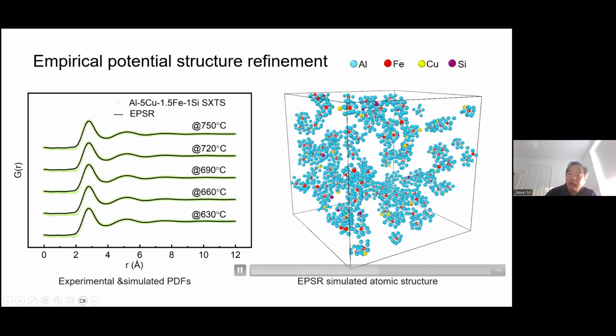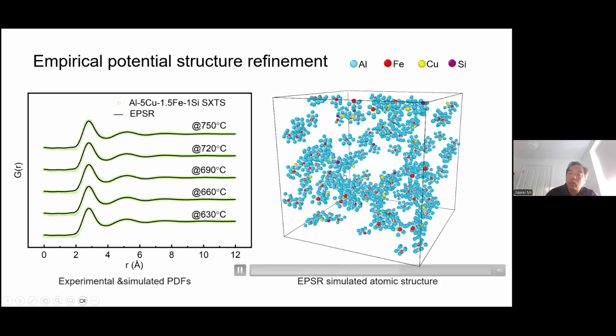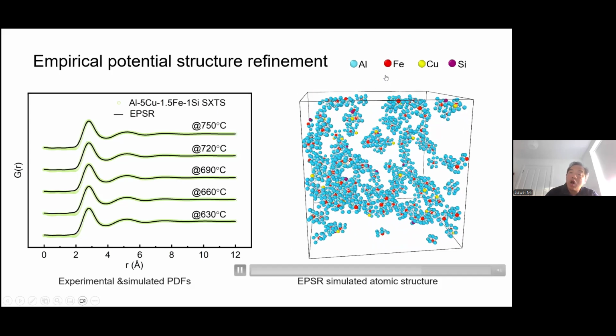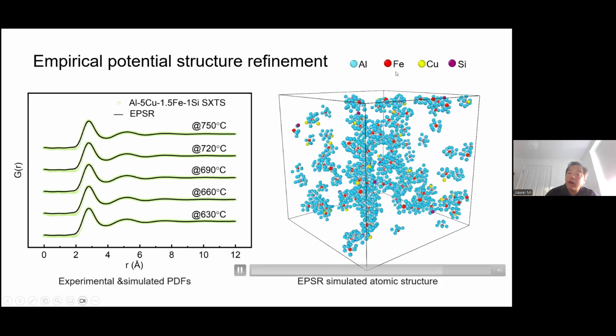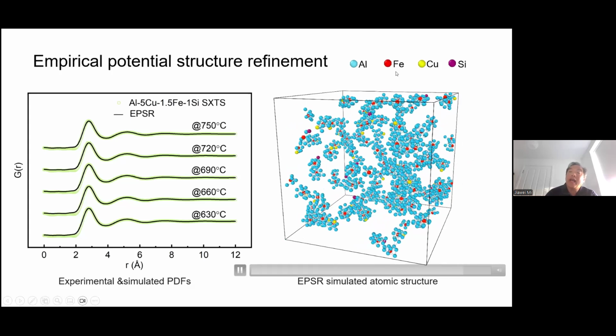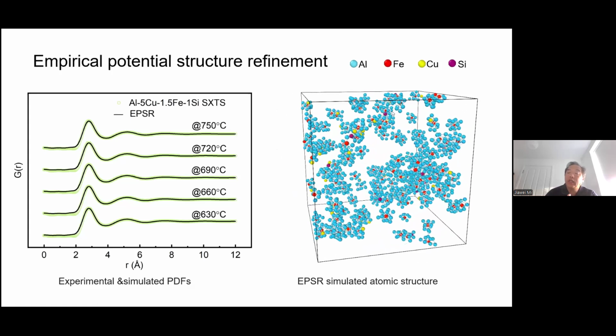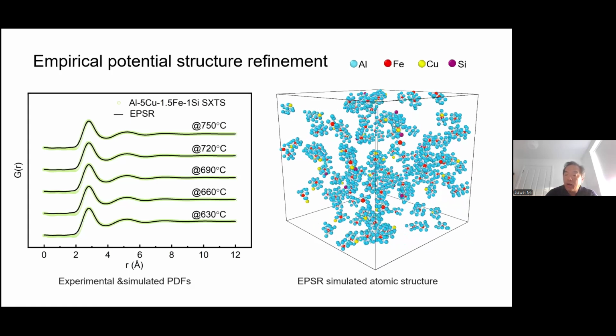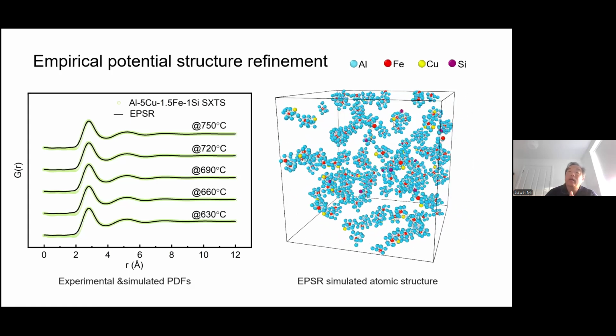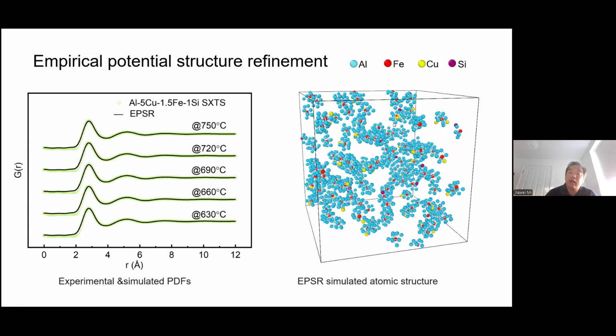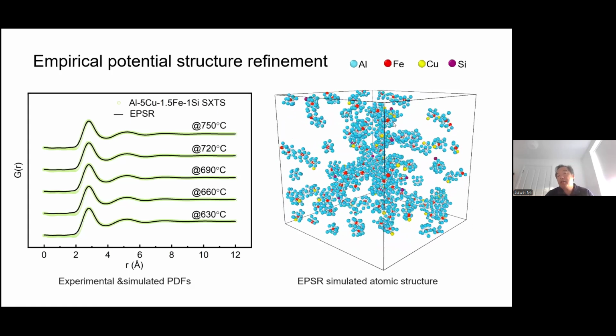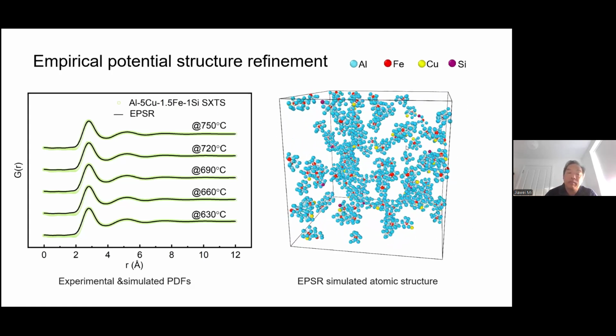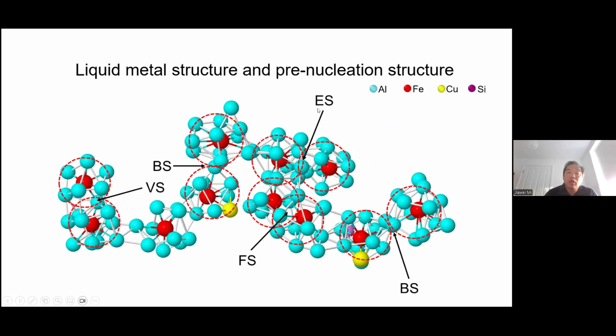The reason we are interested in this is that we wanted to work out what role the iron is playing in nucleating the iron-containing intermetallic phases. When we understand that, we can effectively implement methods to control that formation process. So using this EPSR method, we work out the liquid metal structure.